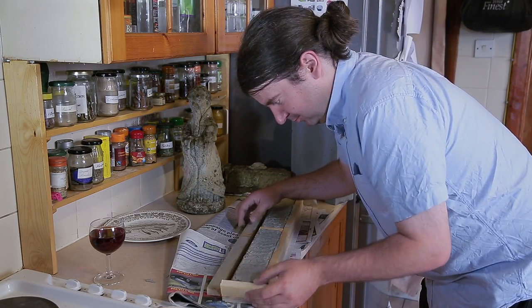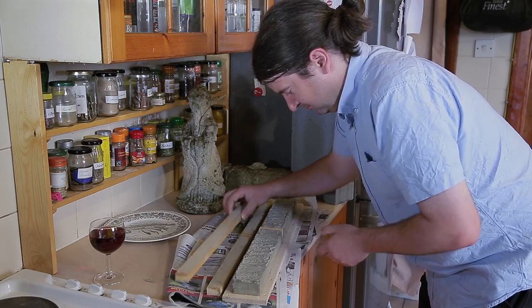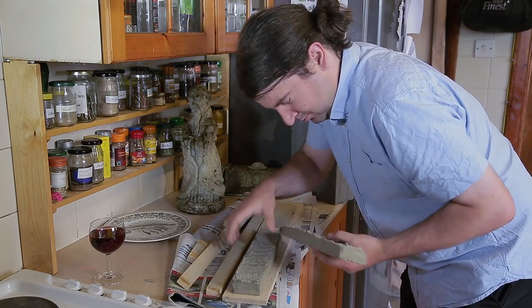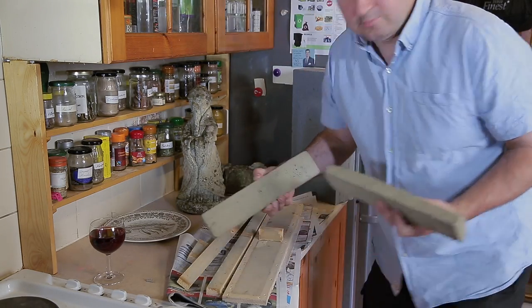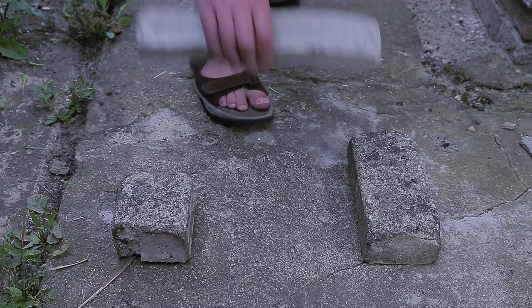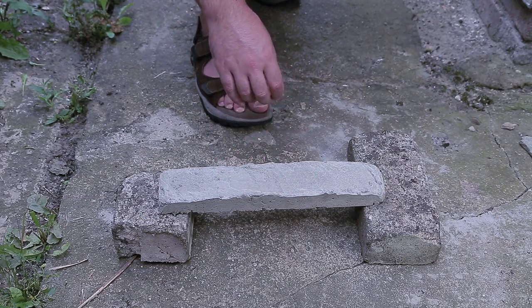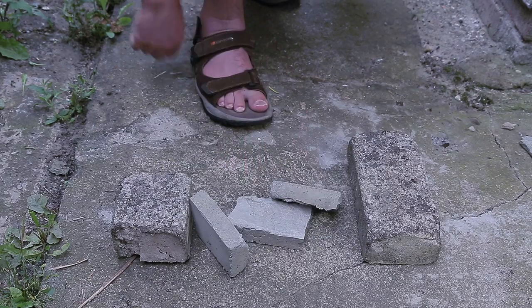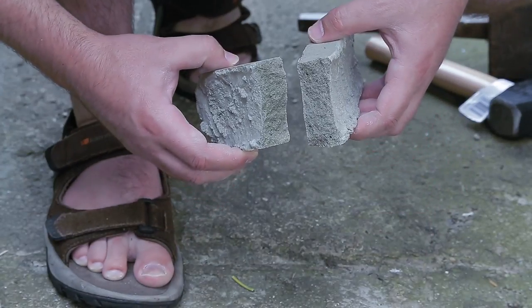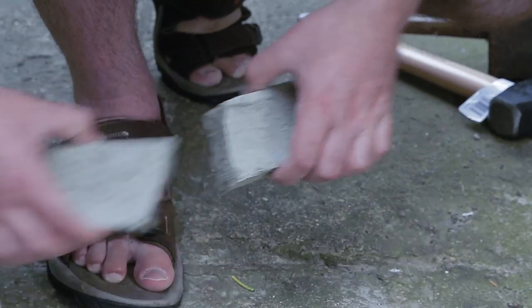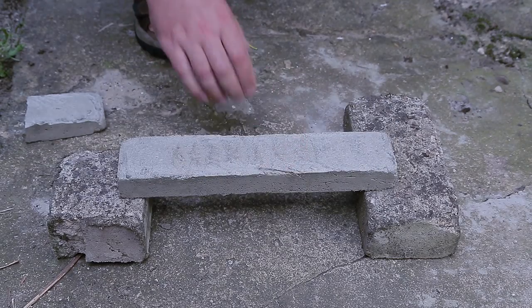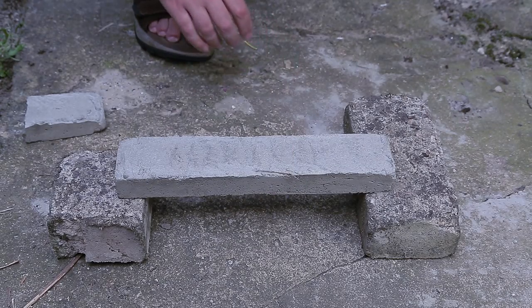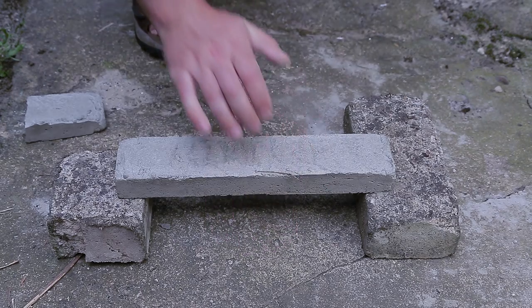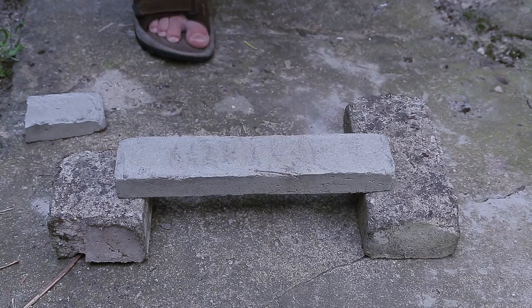Now that our two small beams have had time to harden, we can remove the sides of the mould and take them for testing. Just dropping the first beam into two supports causes it to crack and break apart. The crack was able to spread across the entire cross-section. The beam with steel rods does not break under the same stresses. Even when struck with a hammer, the reinforcement stops cracks from propagating quickly.